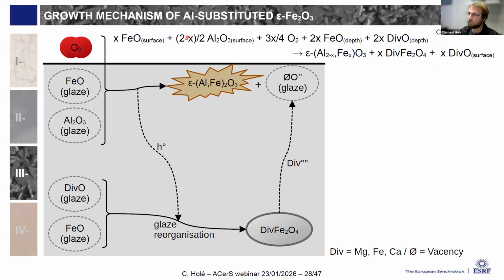So we can, of course, adapt the growth mechanism, including aluminum substitution, because Chinese glazes are aluminum rich. So the aluminum can actually come directly from the glaze and participate in this growth fairly easily.